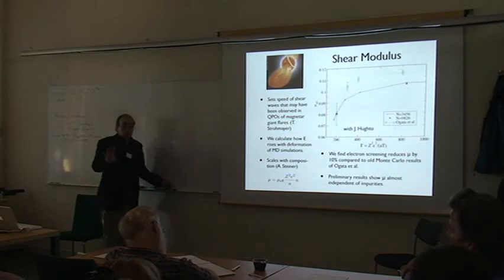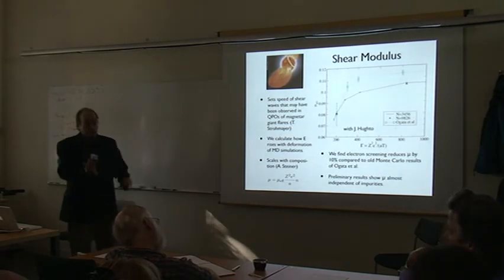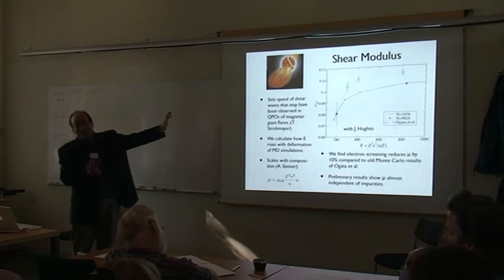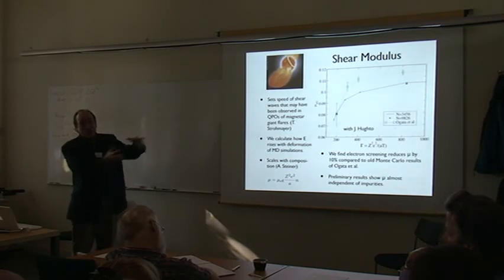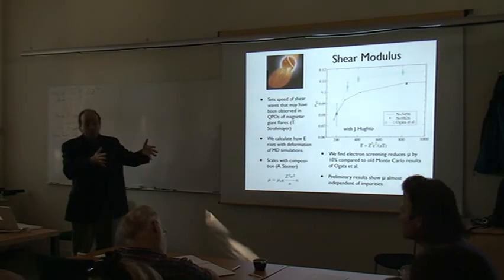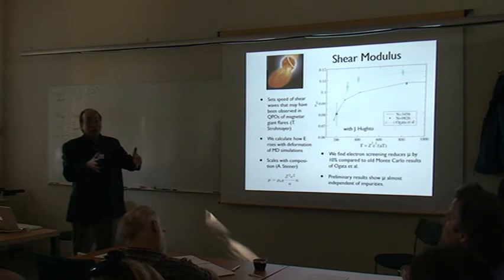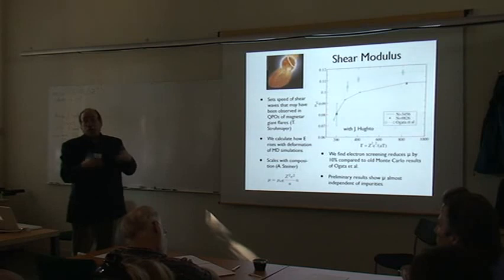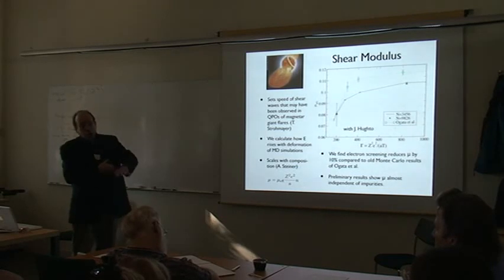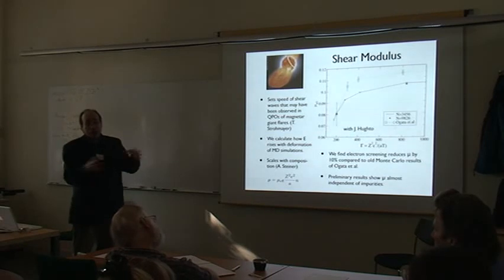That's a good point. I did simulations in the ion coordinates where you ignore the internal structure. And when you shear the system, you generate really strong electric fields inside, and so they will deform the nuclei. The polarizability, for example, of nuclear matter has been neglected. So as you approach the pasta densities, the internal structure and the excitation of the nuclei is probably relevant.